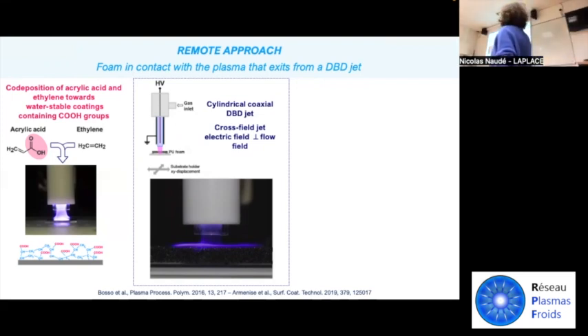In this case, the plasma was fed with helium or argon again, and acrylic acid and ethylene. The co-deposition is almost mandatory to obtain water-stable coatings containing carboxylic groups. When only acrylic acid is used, the water stability of the coating seems very compromised.